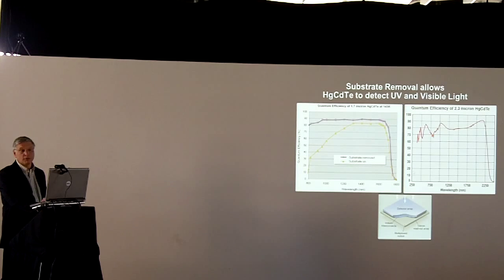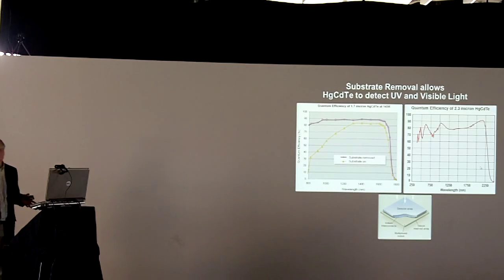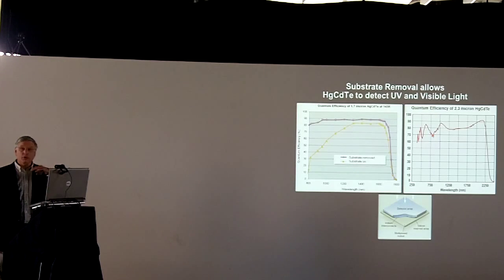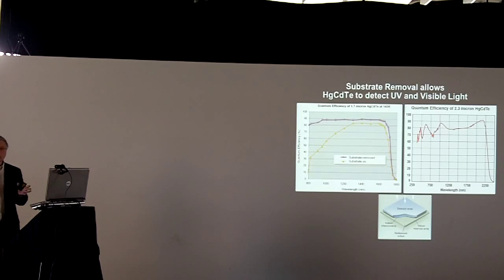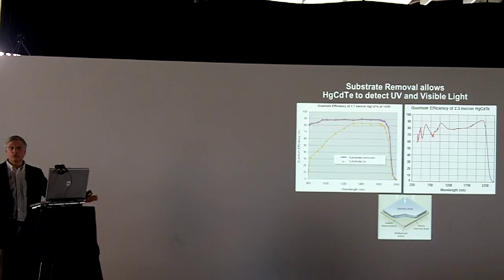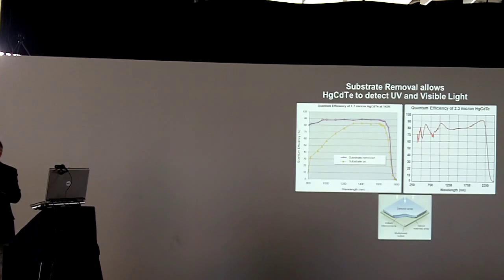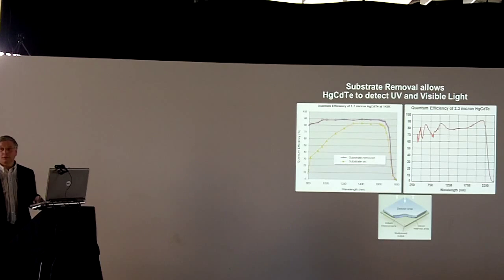And you can actually sense from the ultraviolet all the way out to whatever your cutoff wavelength is in the infrared. So there's more and more instruments now that will use a single detector for combined visible to the infrared. You may have heard of the Moon Mineralogy Mapper. That detected water on the moon, and that was a spectrograph that sensed from 380 nanometers in the ultraviolet out through 3 microns in the infrared with one very small detector in a so-called hyperspectral imager that I think some of the people work on here at Rochester Institute of Technology.